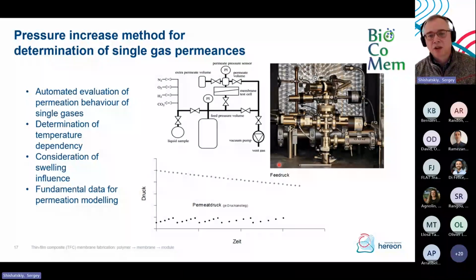And we place the membrane into the so-called pressure increase facility, where we can investigate permeation of different gases, up to 15 gases and one vapor, through our membrane in a temperature range from 1 degree to 120 degrees, and with a feed pressure up to 1,200 millibar. We don't go to higher pressures on this type of facility because then gases start to be non-ideal.